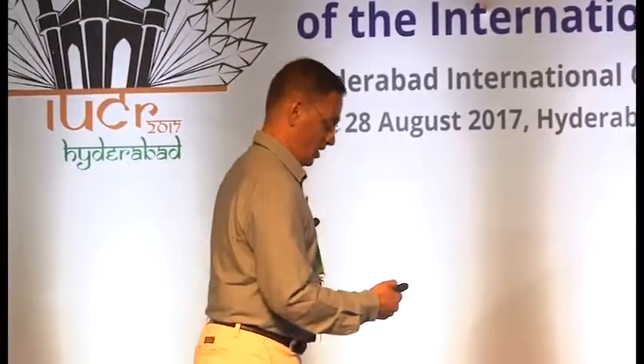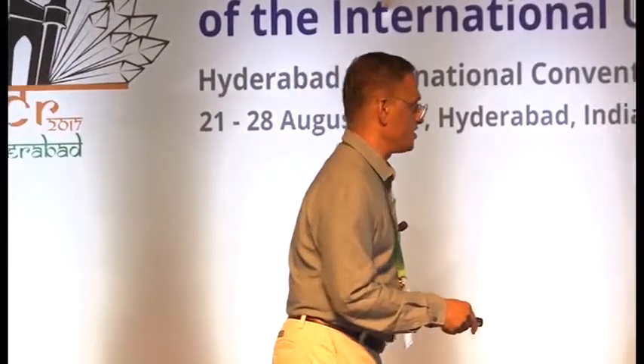That's due to the presence of this particular ligand. You see that the emission of the ligand as well as the MOF are more or less the same. So the emission of the MOF is highly dominated by the presence of this particular ligand. Coming back to it, this also involves Förster resonance energy transfer. I don't want to go into the details of it, but you can increase the quantum efficiency of this particular multiphoton harvesting property, which is about 17%. You can increase it by incorporating perylene and anthracene into it, up to 28%.